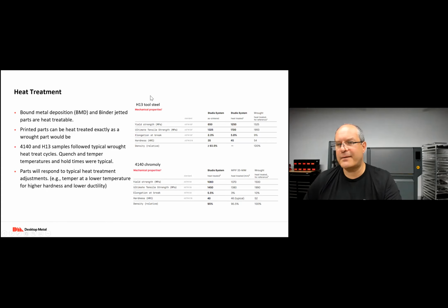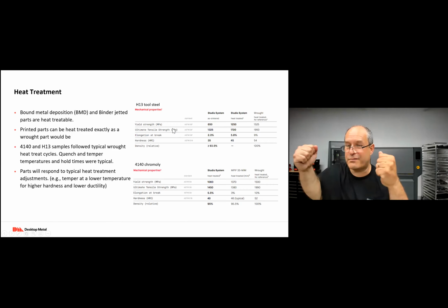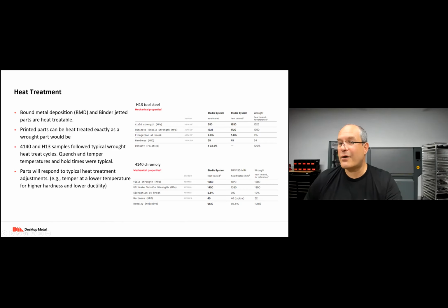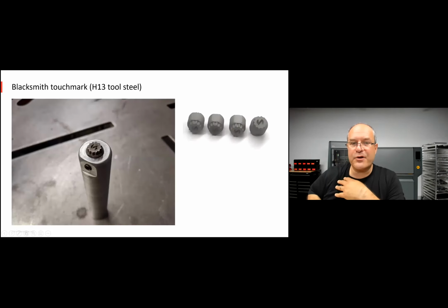So for example, with the H13, notice as sintered, you have a yield strength of 650 megapascals. It almost doubles when you heat treat it. Almost doubles. And the tensile strength before it ruptures goes from 1300 to over 1700 megapascals. So really the parts go, and Rockwell C going up from 35 to 45. So this is a significant jump. 4140 chromoly steel, once you've heat treated it, you have yield strength of over 1,000 megapascals, so a gigapascal, more than a gigapascal, which is pretty crazy. And the Rockwell C as heat treated for 4140 is 40. So you can get some great parts.